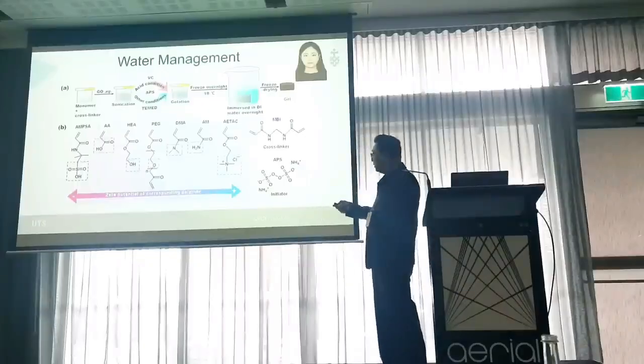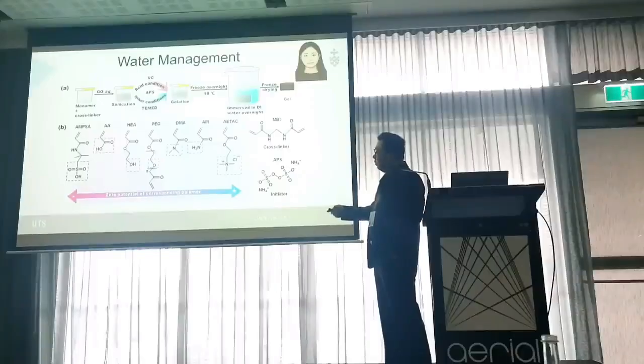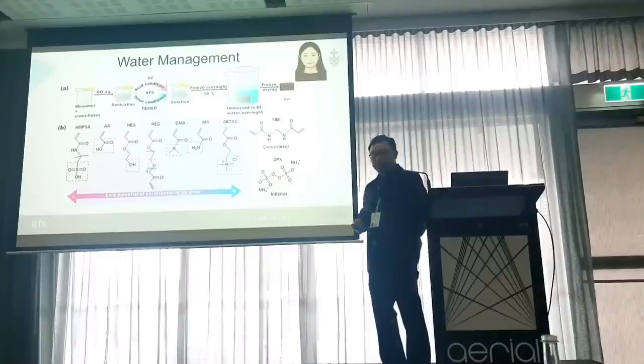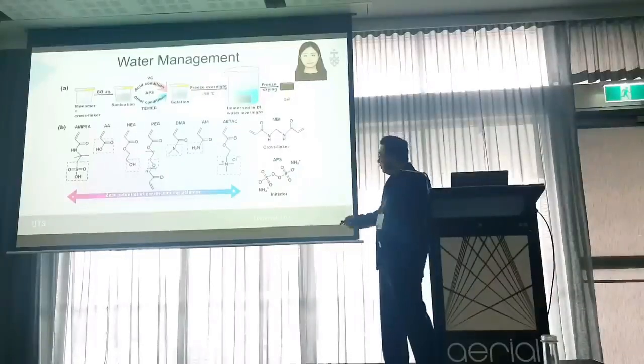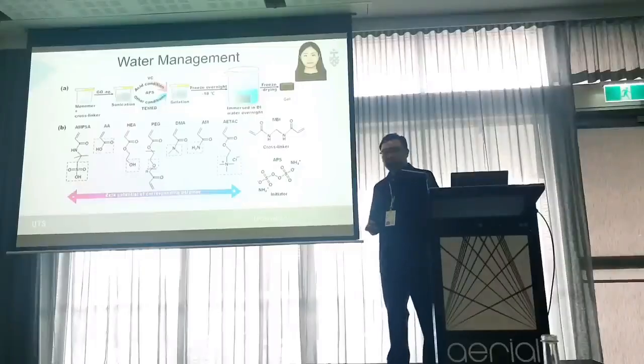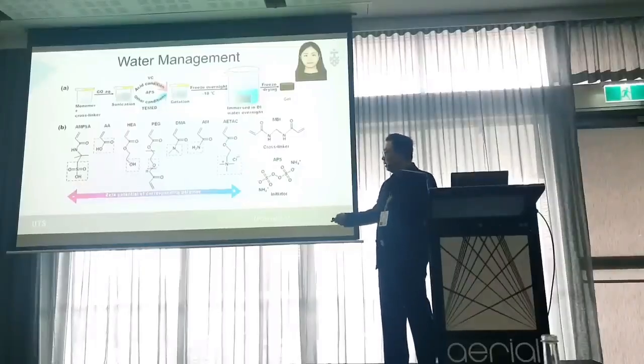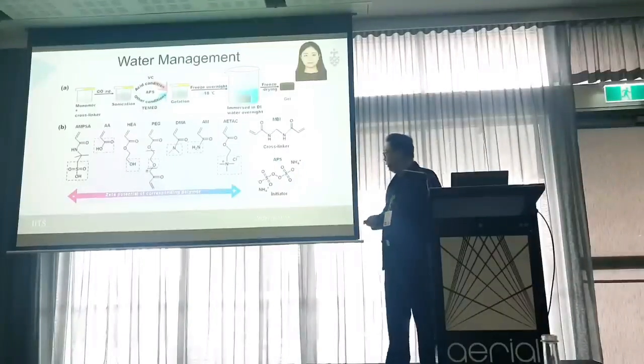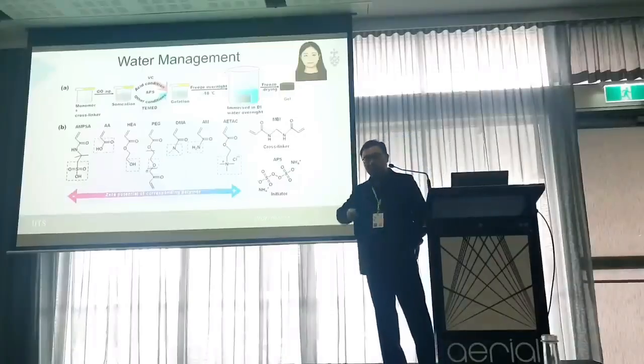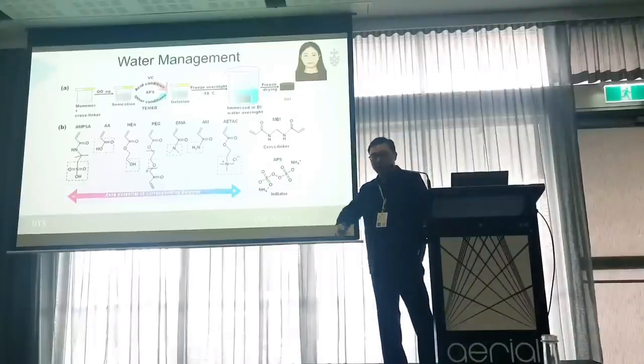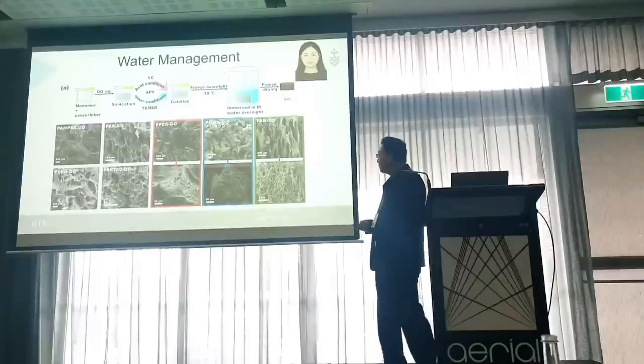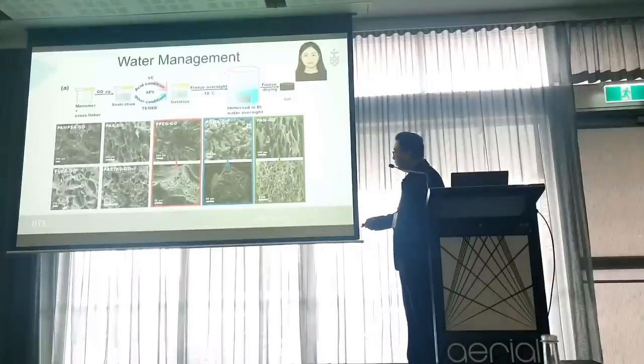So in this study, I asked Shudi to prepare a series of hydrogels. We use the same 0.1 weight percent of graphene oxide as the photothermal material, all the same. But we try different polymer precursors, as you can see, from the negatively charged sulfonic acid group to the positively charged ammonium group, with neutral ether groups or hydroxyl groups. Using the same method, we crosslink them and freeze-thaw them to prepare hydrogels. As you can see, all the hydrogels have the micropore structure.